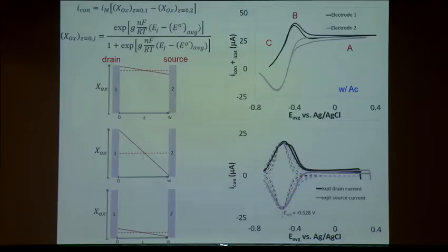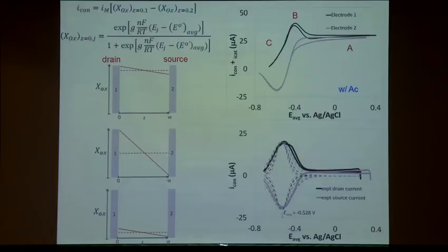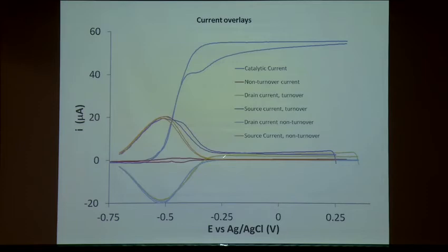And the key thing is we sweep out this peak shape, which is highly characteristic of a hopping mechanism. That is, the ability for electrons to get from one electrode to the other is dependent upon the redox gradient that exists between the electrodes. So the last point I want to make on this slide is that we overlay these data here. The midpoint potential of the catalytic curve is about here. And the formal potential of these gate measurements is much more negative. The gate measurement peak is also a lot wider than expected based on fitting the catalytic curve. And so what that points to is that there may be more charge transfer mediators in the biofilm that can engage in electron transport through the biofilm in a source drain measurement than are actually being utilized by the biofilm during acetate oxidation.